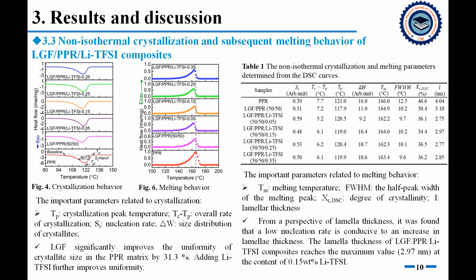Non-isothermal crystallization and subsequent melt behavior. From the crystallization curves of our samples, we obtain the relatively important crystallization parameters, such as the crystallization peak temperature, crystallinity, temperature, overall rate of crystallization, nucleation rate, and size distribution of crystallites, respectively. We have found the evolution of these parameters.